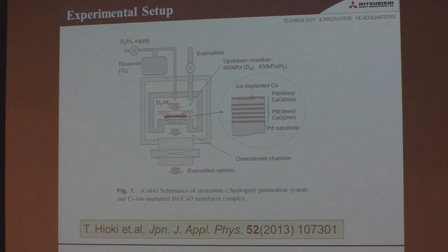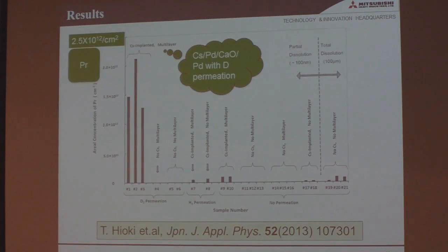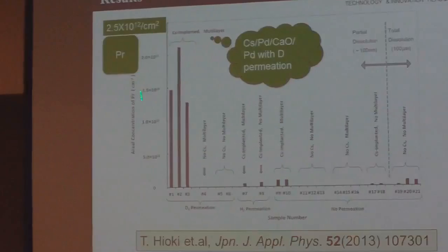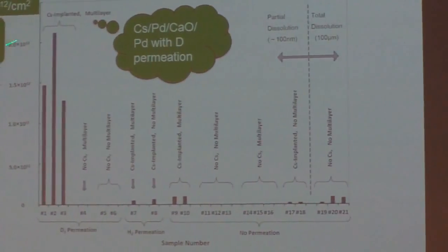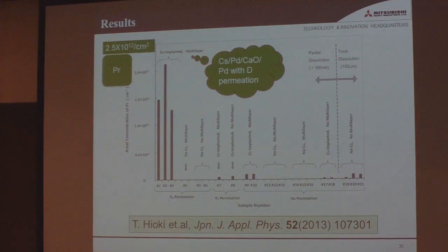And their experimental apparatus is here. They gave the D2 gas flow like this, and they used a very similar multilayer thin film. Of course, they fabricated this thin film themselves. And this is their result. They performed three foreground experiments: cesium, palladium, calcium oxide, palladium with D2 permeation, three times. This axis means praseodymium, and here is 2.5 times 10^12 atoms per square centimeter. That is the foreground experiment, and the other is this region, the no-permeation results.